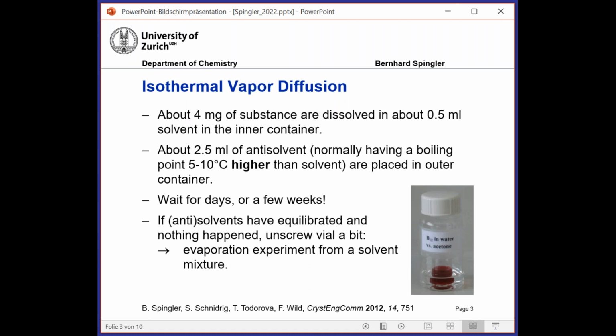So what we do is we have our simple recipe. We have an inner container, which you see on the lower right, where there is the compound to be crystallized. In this case, it's vitamin B12 because it has a nice color. And normally we take about 4 milligrams of substance. The important point is that we want to start with a clear solution. And if we don't have a clear solution, we will filter it. Then we dissolve it in about 0.5 milliliter of solvent in the inner container. And then we put about 2.5 milliliter of the anti-solvent, normally having a higher boiling point, about 5 to 10 degrees higher than the solvent, and place that in the outer container.